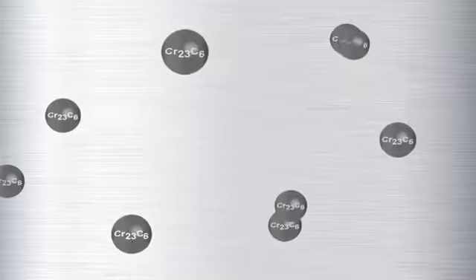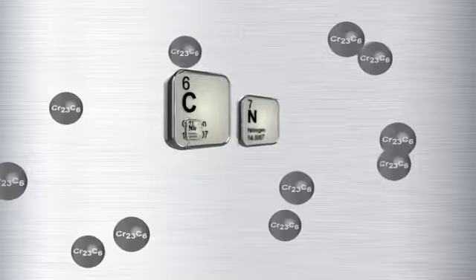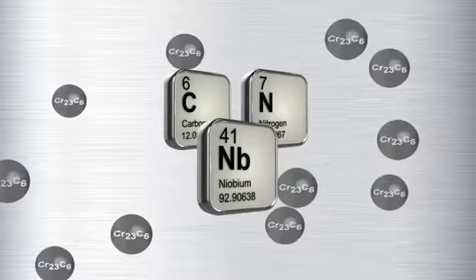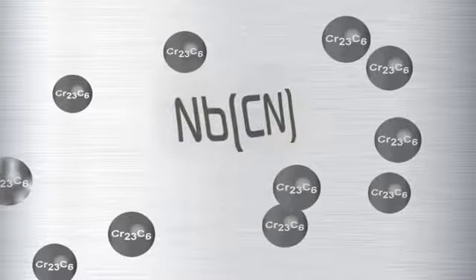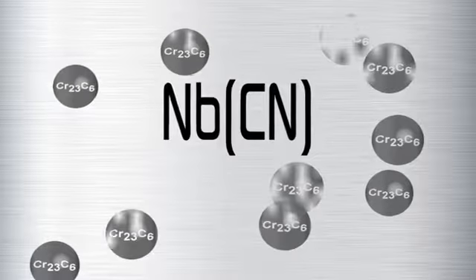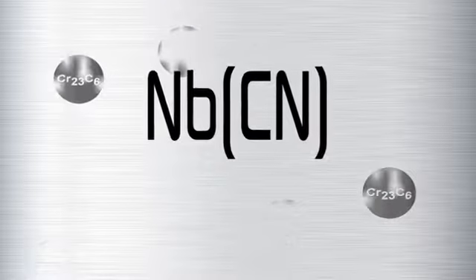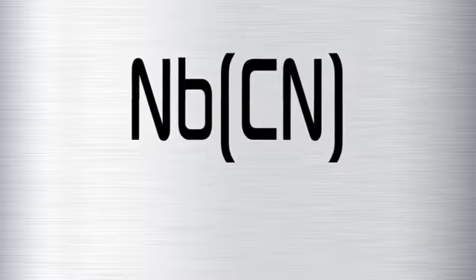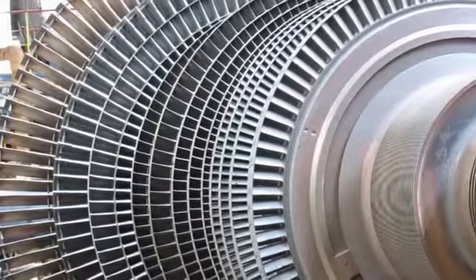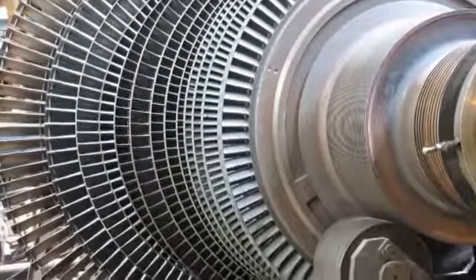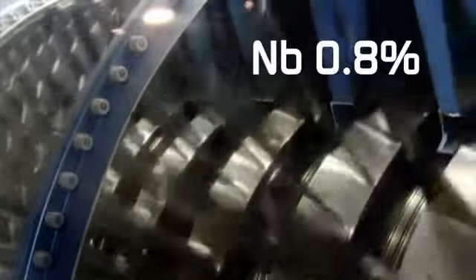Furthermore, by mopping up excess carbon and nitrogen, it minimizes the precipitation of complex chromium carbides during heat treatment or welding. This in turn prevents local loss of chromium in the matrix, which can lead to intergranular corrosion, pitting corrosion, or welding difficulties. Niobium also plays a special role, sometimes in conjunction with molybdenum, in increasing creep strength through precipitation hardening in certain austenitic stainless steels intended for high temperature application. A typical niobium level in this class of steel would be 0.8%.